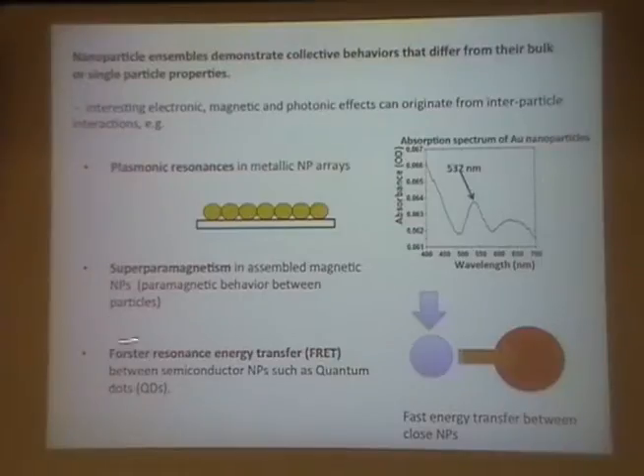And the other one down here, which I think is quite interesting too, is this Forster resonance energy transfer. This is an effect between semiconducting particles, like the quantum dots. So if one quantum dot absorbs a photon, so it would be excited, it could then decay and produce an emission. Or there could be an energy transfer between this one and a nearby quantum dot, say from blue. It will absorb in the blue and emit a lower energy photon, which will then immediately be absorbed by a nearby quantum dot, without emitting first. So that's the Forster resonance energy transfer.